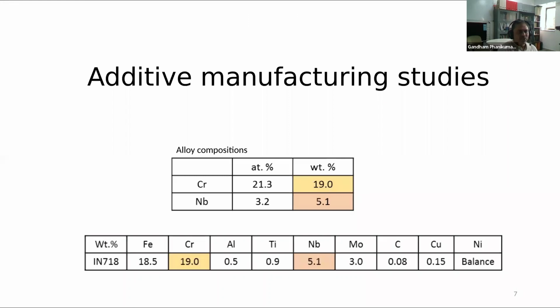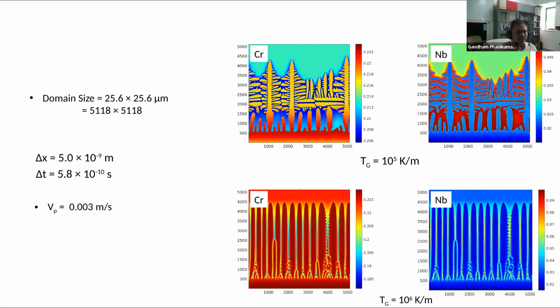Now in additive manufacturing, you can do that. The challenge in the past was that there were many elements. You can make out that a superalloy will have so many elements, so simulating microstructure evolution with all the elements is a bit costly. But today it's possible, so we have taken that up to show you. Seven elements can be considered, and Mohan has done his simulations on a multi-component alloy. You can simulate the microstructure evolution in the computer at different processing conditions, like the temperature gradient, 10 to the power of 5 Kelvin per meter, 10 to the power of 6 Kelvin per meter.